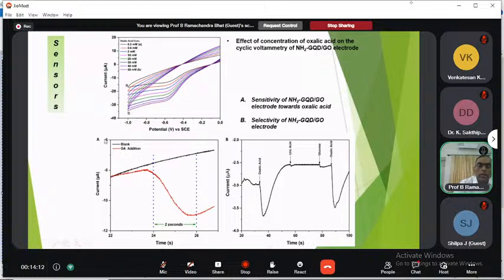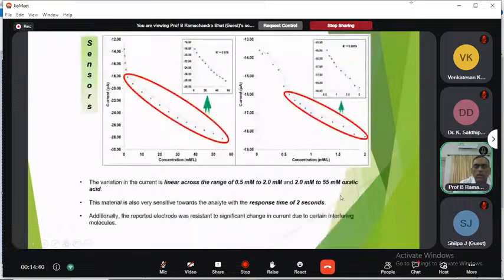And the beauty here is that the response time is less than 2 seconds. As for selectivity, you can see the activity with oxalic acid, and the others, uric acid or glucose, which are normally present in the blood or the urine. You can check with those, and it gives a response to oxalic acid only.